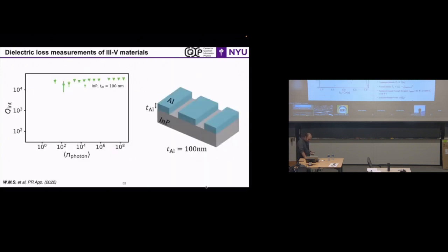One question that we had ourselves, which was a really good exercise, and I'm going to wrap up with these last few slides, is that we said, okay, indium phosphide, bare material. What is the quality factor of indium phosphide? The one that we can measure in our lab is, I don't know, 20, 30,000. So, okay, great. Let's make it on a new substrate, on an indium arsenide substrate. So we measured it, and it was a factor of 10 lower.